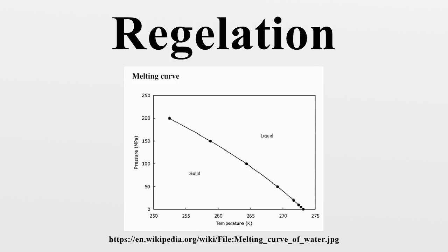In 1998, using atomic force microscopy, Astrid Döppenschmidt and Hans-Jürgen Butt measured the thickness of the liquid-like layer on ice to be between 12 nanometers at -24 degrees Celsius and 70 nanometers at -0.7 degrees Celsius. Surface melting was found to begin at temperatures as low as -33 degrees Celsius. The surface melting can account for the following: low coefficient of friction of ice, as experienced by skaters; ease of compaction of ice; high adhesion of ice surfaces.